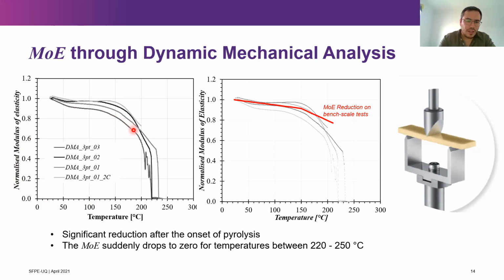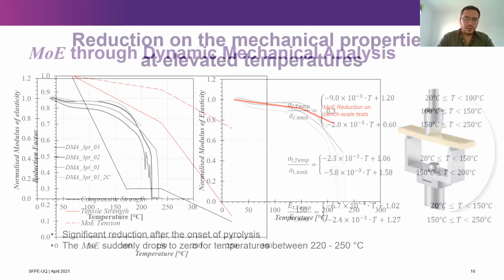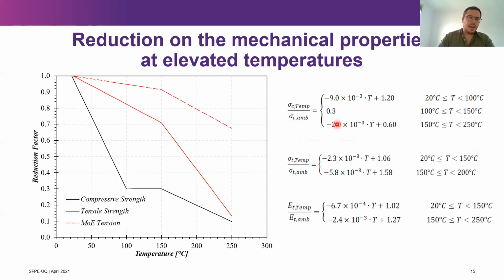And these are the results of the DMA, and this is the reduction in the MOE at bench scale, which told us that the results match pretty well both medium and small scale. With all that information, we created some reduction factors for bamboo at elevated temperature. Reduction factors for the compressive strength, which is the black line here. Reduction factor for the tensile strength, which is this line, and then obviously the reduction in the modulus of elasticity.